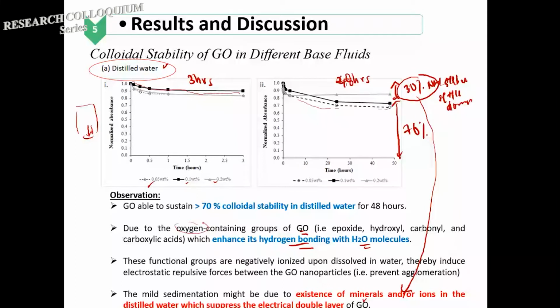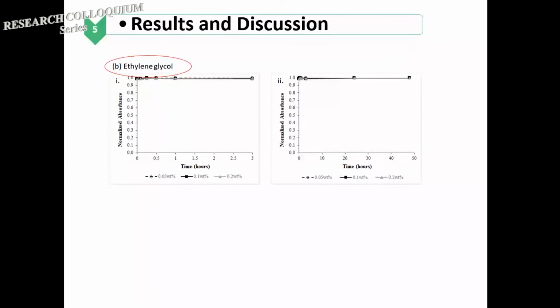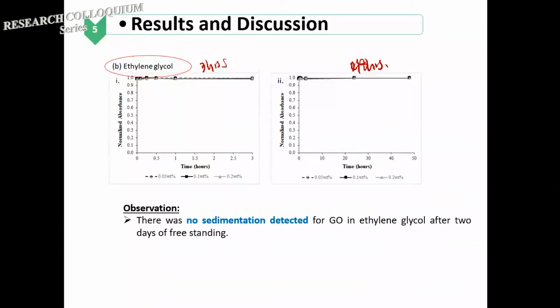For the next one, we're working on ethylene glycol. Interestingly, we found that when you put the graphene oxide into the ethylene glycol, there is no sedimentation, no matter whether it's 3 hours or up to 48 hours. You can see the nanoparticle remains 100% suspended in the solution. So it's a super successful one. We were very happy when we saw this at the time. There was no sedimentation detected for the graphene oxide in the ethylene glycol,